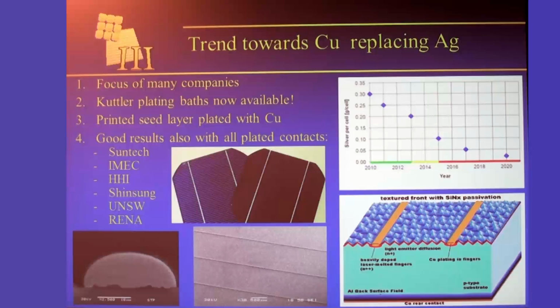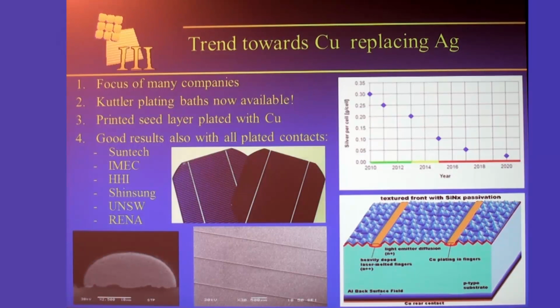Prior to this, we've been able to use those plating baths, but we've always had to send our people across to Suntech in China to use the plating baths there. So probably the preferred approach at the moment is to print a seed layer, a very thin seed layer. You can print it by a range of approaches. You can either screen print a seed layer, or you can use inkjet technology, aerosol technology to deposit a thin seed layer that doesn't use much metal, and that provides the interface to the silicon, and then you plate the copper on top of that seed layer. So quite a few companies are looking at that approach, and there's been some good results reported recently. And so that's one direction it could go in.